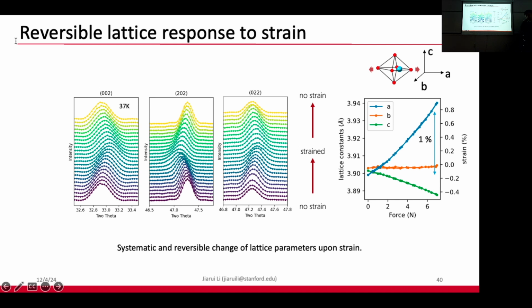So what's causing this reversibility? Why is it so resilient? We believe that it's the reduction of one dimension. Since we reduce the thickness dimension down to a nanometer, we get more flexibility to release the strain through the interface with the vacuum. Yeah, and I can show you later. I didn't put it in my slides. We have a thickness dependence of how much it can go. When above 50 nanometer or 100 nanometer, it behaves the same as the bulk. But if you go down to 10, 20 nanometer, it's enhanced.